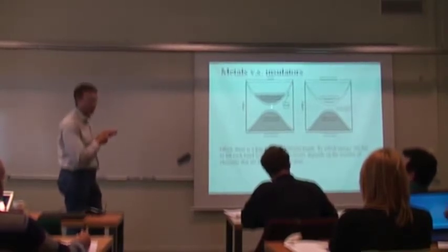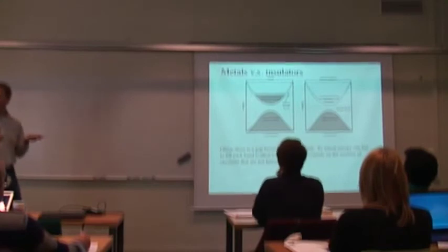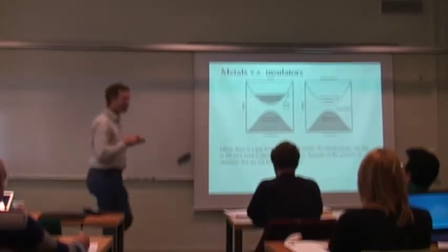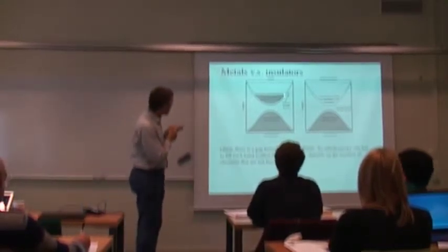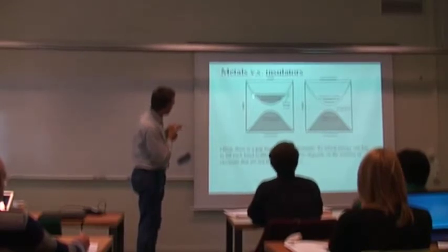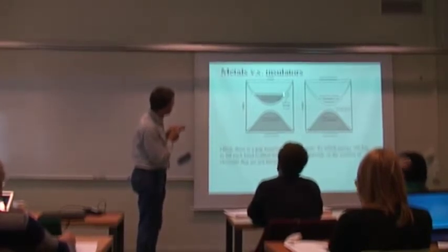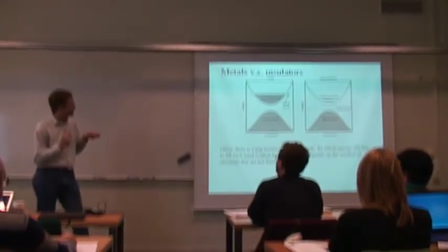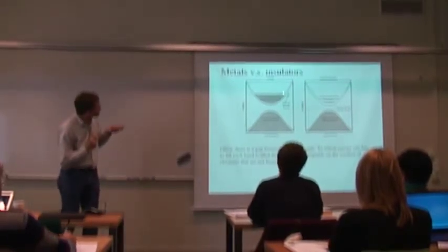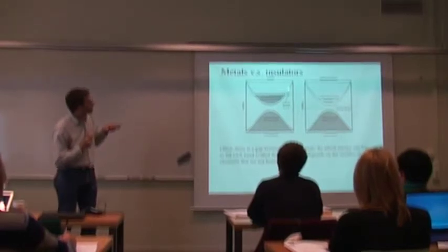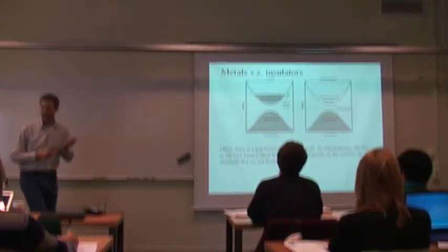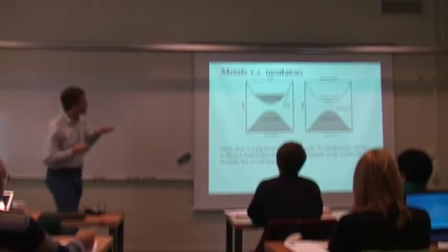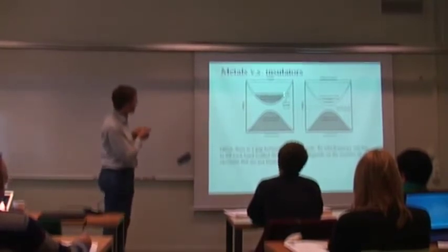the conduction band is partially filled. And if I now apply an electric field, what will happen is that some electrons which are lying in these states close to this Fermi level will just move to a different state here. So applying a very small electric field, I can move these electrons up a little bit, towards here, and once they're here, they can actually conduct. And so in this region here, I can just apply a tiny field and move my electrons around a little bit, and I will get a current.